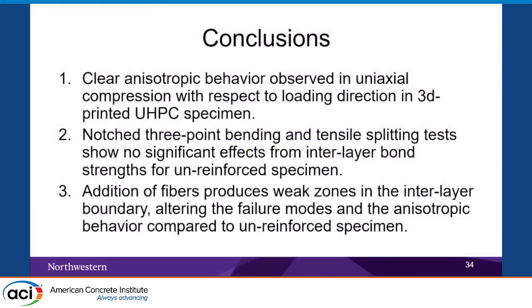Let's look at some conclusions. In conclusion, we have a clear anisotropic behavior when we test the uniaxial compression samples. For notch 3-point bending and splitting, we have no significant effect from the interlayer bond. But adding fibers creates weak zones in the interlayer, which alters the failure modes and the anisotropic behavior compared to unreinforced specimens.